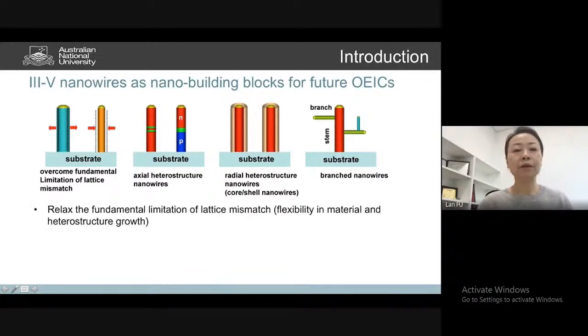Firstly, because this is a one-dimensional nanostructure, when we grow them onto a substrate, it can relax some fundamental limitations of the lattice mismatch problem that arises when we grow a planar structure on a substrate with a very big lattice constant difference. Because of that, it enables us to grow a greater variety of materials on the substrate, or even on a foreign substrate. And also in terms of creating different structures, such as the heterostructures you may have heard about, you have more flexibility to grow those kinds of things, right?